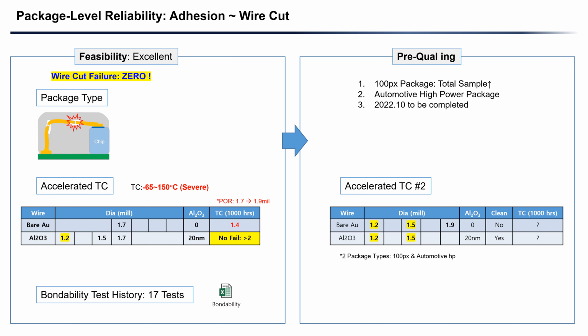Reliability testing was done for the packages susceptible to wire cut failure mode during accelerated thermal cycles. Very, very serious temperature swing from -65 all the way up to 150 degrees C. The conventional wire started to fail at 1,400 cycles. However, aluminum oxide coated wires survived more than 2,000 thermal cycles. Please note that the diameter of the aluminum oxide coated gold wire was much smaller than the bare gold wire cases, 1.2 versus 1.7. Right now, apple to apple comparison testing is going on, 1.2 to 1.2, 1.5 to 1.5. Diameters are the same for both no coating and coating cases of aluminum oxide.